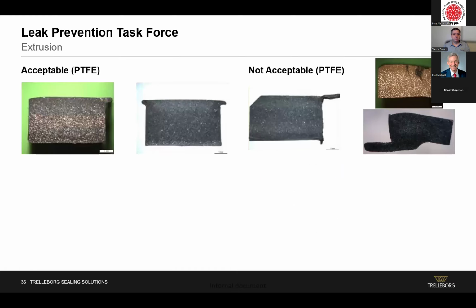So the first one is extrusion. I have some pictures of PTFE seals, with some acceptable extrusion on the left and not acceptable extrusion on the right. With PTFE seals and really high pressures, we can expect some extrusion, or creep as we call it, as the material moves over time with pressure, heat, and wear. But if there's too much extrusion, that can cause the seal to start leaking and no longer perform as designed.